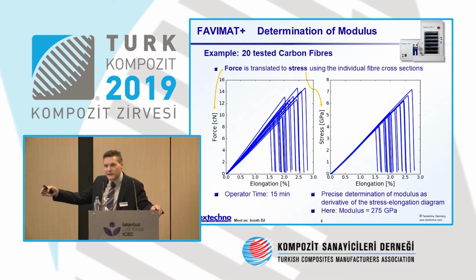Now we've integrated the diameter measurement, it's performed on each single fiber, and this translates the force to the right-hand side diagram, where force is now expressed as stress. So it's normalized to the cross-sectional area. And now you see that there's actually a huge variation from fiber to fiber in terms of cross-section. But when you normalize it to the cross-section and express it as stress, you get a very smooth curve where all the fibers line up on top of one another. And it gives you a very fast and direct measure of the modulus, which is of course the most important property of a carbon or glass fiber, being here about 275 gigapascal.